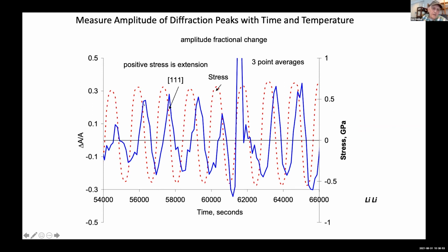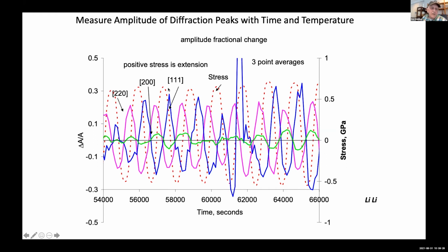You might notice that the amplitude is 90 degrees out of phase with the stress, and I would contend that that argues that the amplitude is driven by strain, because in this case, if we're in the plastic region, stress is in phase with the strain rate, and the strain rate's 90 degrees out of phase with the strain. So this would be the strain in the sample, and this is for the 111 peak. If we look at other peaks, they're either in phase or out of phase with the 111 peak, showing that some peaks grow when stress increases or strain increases. Some peaks shrink during that time.